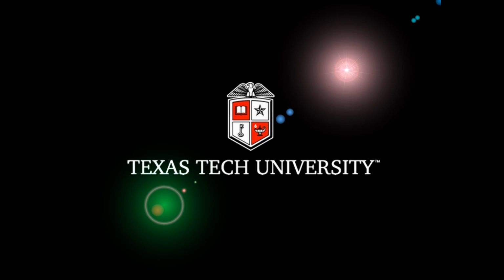In 2008, Kapnistos and colleagues researched the stress relaxation behavior of ring polymers, which do not have chain ends. They found that the ring polymer exhibits self-similar dynamics yielding a power law stress relaxation. And the reason why non-concatenated rings do not trap themselves in a melt but relax as a self-similar power law without a rubbery plateau instead is still not understood.